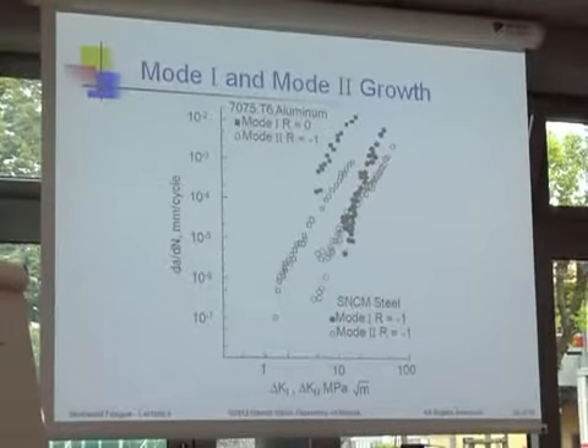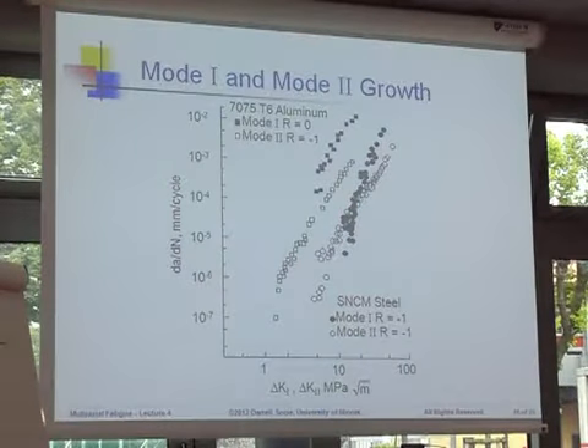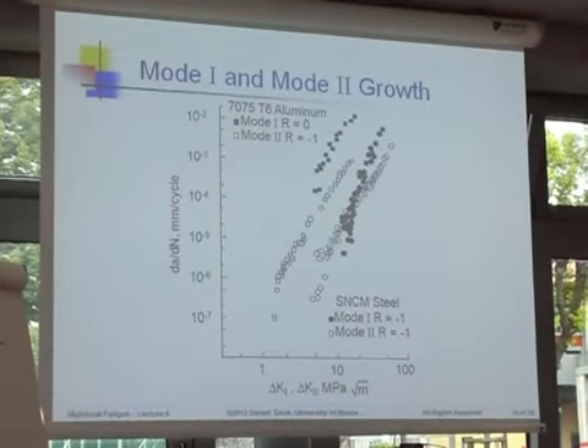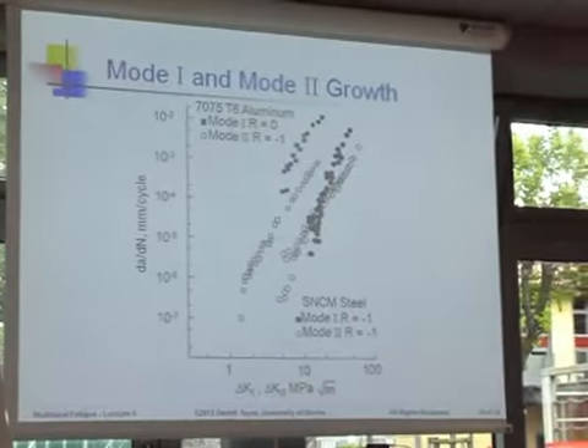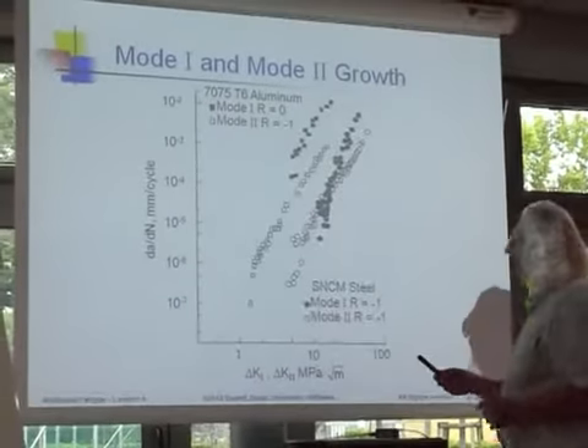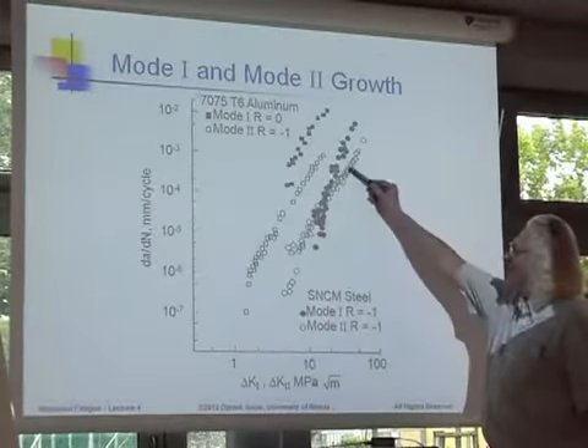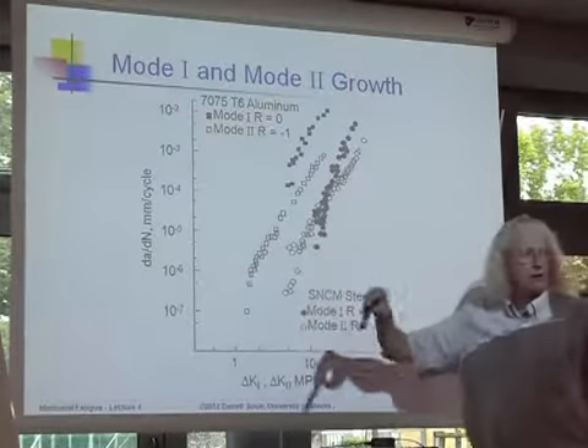Here's just even more data, and you can find anything you want in the literature. So if you build a new model about long crack growth, and you want some data to show your model is correct, you can find it. Doesn't matter what direction your model goes, more or less, because there are very few careful experiments. So here you can see, well, okay, I've managed to find some data that shows the mode 2 and mode 1 growth rates are about the same.